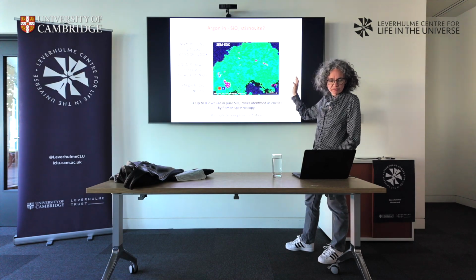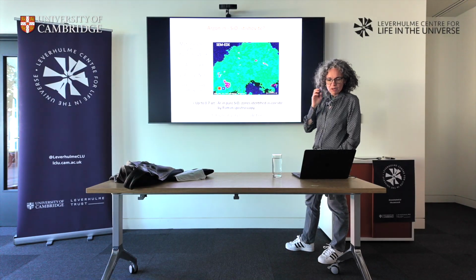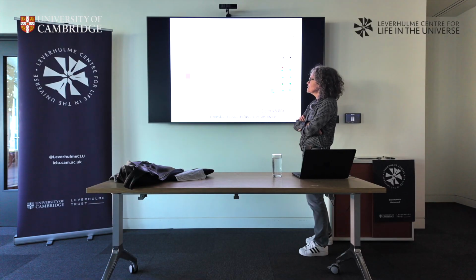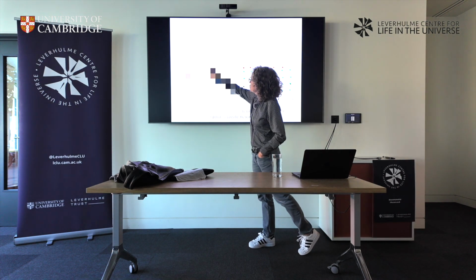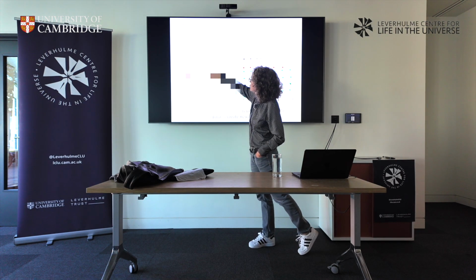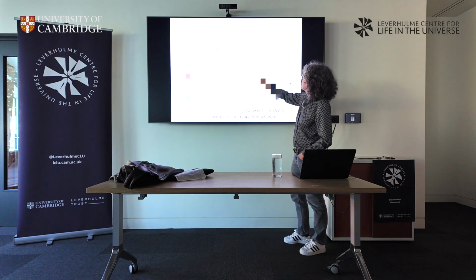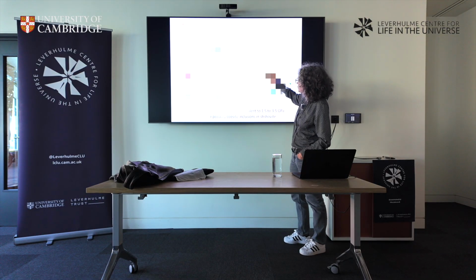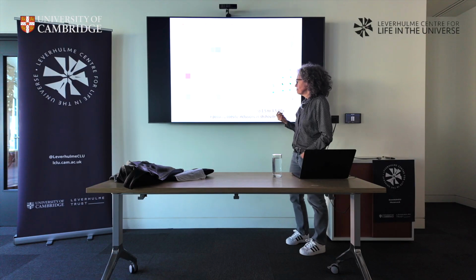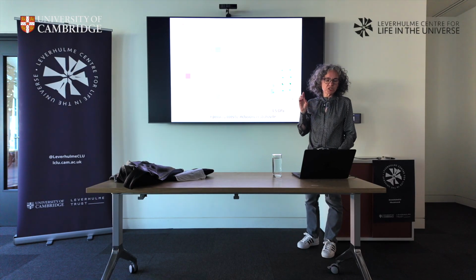Initially, I thought it was all stishovite, because when I first looked with Raman in the lab, it was stishovite. So we have Raman spectroscopy data, and interestingly, in this coesite mixed with stishovite sample, the coesite peaks are a little bit shifted compared to room pressure coesite. Depending on where you look, it's 1 to a few GPa. I don't know if it's a chemical pressure, or if the coesite is an inclusion in the stishovite. That needs to be looked at. I'm not sure yet.